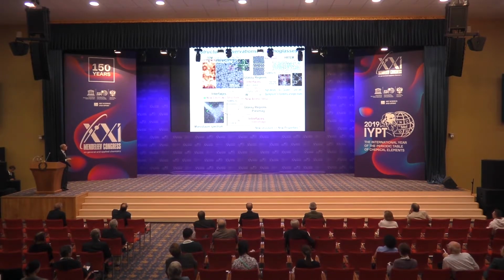And one can directly see this change by looking at a two-dimensional system, two-dimensional silicon dioxide. Here is a glassy region, and here you see such an interface, and you can see that it's less dense, and the number of nearest neighbors is reduced.